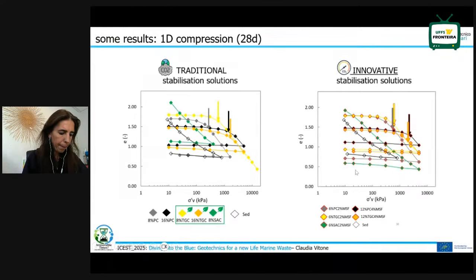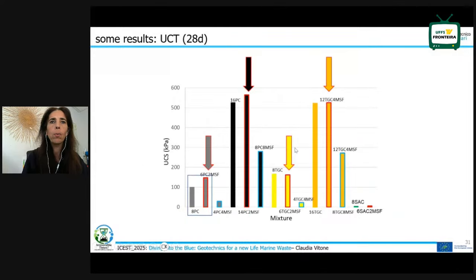And this is what happens when we replace part of the cement with the mussel shell powder. You can see already here that the behavior is extremely similar in one-dimensional compression. These are instead some results of unconfined compression tests, where the red contour means the mixtures where the cement has been replaced by the shell powder. As you can see here, compared to the control mixtures, the gray, the black, the yellow, the mixtures including shell powder with low cement, so in place of 16% of cement, we have 12 plus 4, we have a very similar strength, sometimes even higher.